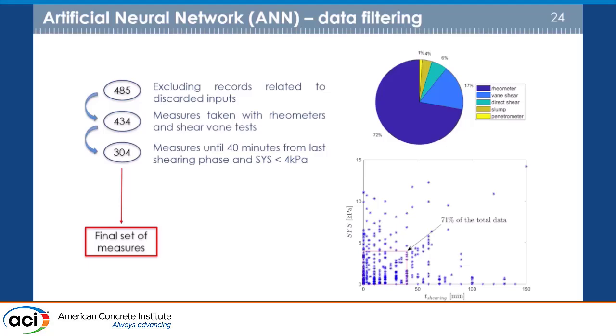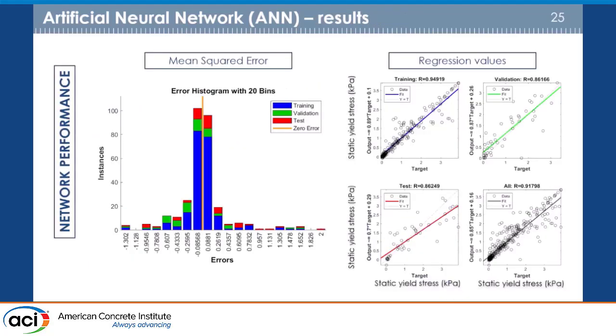But this shows you that, starting already from a broad surveyed literature which yielded us only 485 records in terms of information on the mixes, if you have to go down and clean up to what you really need and have all the complete information, you go down to 304 measurements for which you have the complete information, also about the time at which it was measured. And most of the measurements, as shown there in the pie chart, were done on a rheometer, so it was okay for us. Well, these are just the results for the calibration of the neural network and the validation of the error. We use the usual tools for calibration, testing, and training.